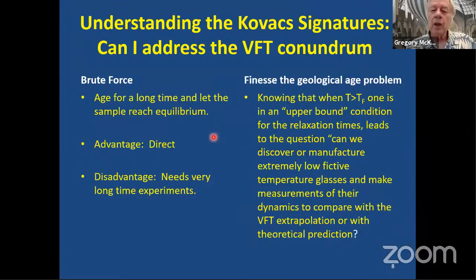Okay, so one way to do it would be to do experiments like the intrinsic isotherm, and that would be to do it by brute force and age for as long a time as you're willing to wait and let the sample reach equilibrium. Of course, the advantage of that is it's direct. The disadvantage is it needs very long time experiments. And in fact, it's very hard to get much further below the glass transition than maybe 15 or so degrees before you run out of time. And I'll show you why that is the case. We call that the geological time or astronomical time problem in the experiments. And I think most students don't want to go more than about a few weeks for their experiment, well enough, a few years.